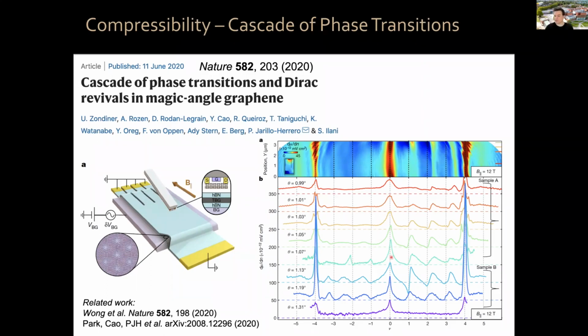Okay, the system is breaking some symmetries and is flavor polarizing in some directions. These symmetries which the system has are spin and valley. The electrons in graphene can have spin up and down and valley K and K prime. That's 4. That's why there are 4 electrons per Moire unit cell. You know, 4 appears many times in this magic angle twisted bilayer graphene business. So as you go through each integer, the system decides to flavor polarize in one of those directions. I will mention a little bit more about that later.